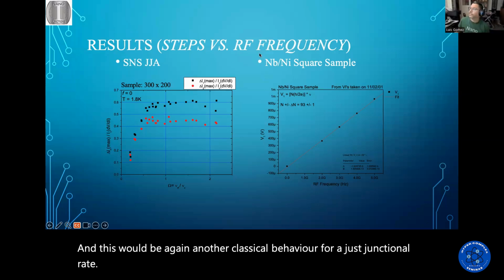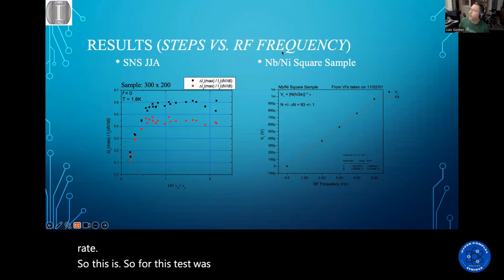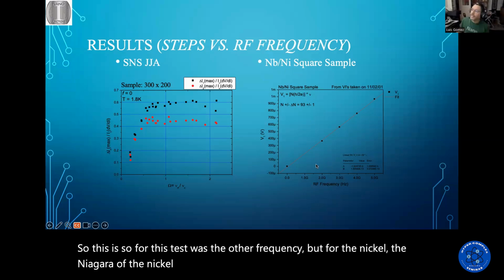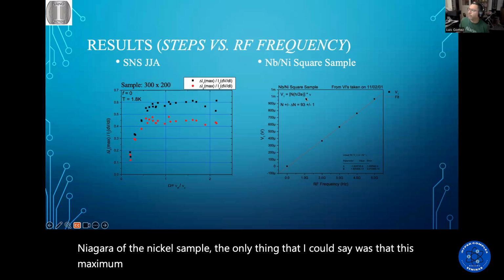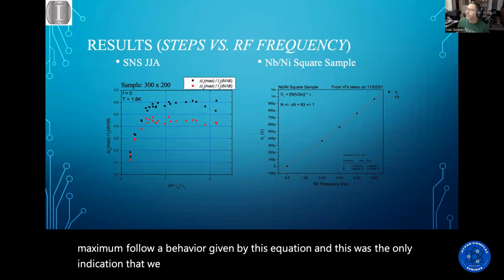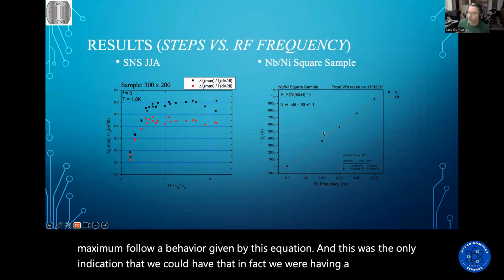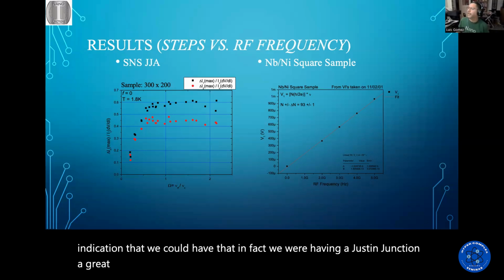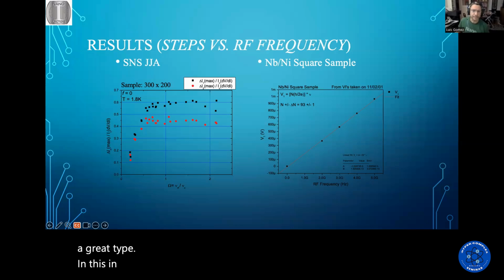So this is sort of the steps versus the RF frequency. But for the niobium over nickel sample, the only thing I could say was that this maximum follows a behavior given by this equation. This was the only indication we had that we were in fact having a Josephson junction array type in these samples.